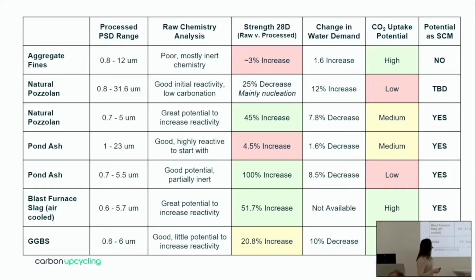So we looked at everything from aggregate fines to natural pozzolans, pond ashes, blast furnace slags, and ground granulated blast furnace slags. In the strength column, you see everything from just a couple percentages in increase in strength all the way to 100% increase in strength with one of the pond ash samples. So that's the one parameter to consider. Then we look at the CO2 uptake, and this is where we did a bit of a chemical analysis. So you can see that some materials don't have a lot of strength, but they have a high capacity to mineralize CO2. Other materials have a lower possibility to capture CO2, but we can double their strength performance. So there's a balance here to strike between what we can achieve from a material performance perspective and what we can capture in terms of CO2. So these are the two parameters we really look at in determining the feasibility of a material.